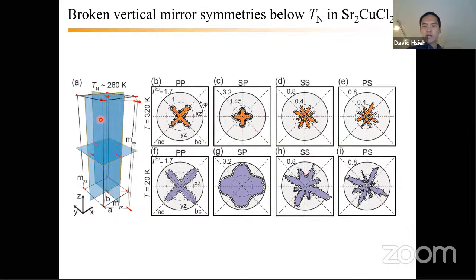Here, again, the data is a bit weak, but I hope you can make out that what used to be four equal petals has acquired this alternating amplitude. You have small petal, big, small, big, and so on in both the SS and PS channels. And here you can see that, yes, I've broken my AC and BC mirror planes as I expect from the Néel order, but I also break the XZ and YZ mirrors, which you don't expect from the Néel order. The Néel order should preserve this mirror, and it should preserve this horizontal mirror as well. So somehow below T_N, even in the raw data, one sees that all of the vertical mirror planes have been broken, and that's not what you'd expect from the Néel structure.